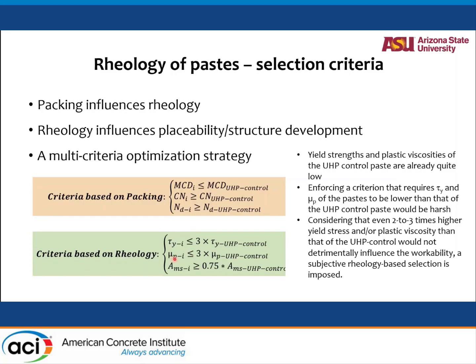For the criterion based on rheology, just saying that the yield stress of my mixture has to be less than the yield stress of the control is not very efficient, because even two to three times higher yield stress or plastic viscosity would not detrimentally influence the workability, especially when your packing is so high, right? So we took this number as 3, and we did experiments to show that you actually can have good workability in that case. So we used a factor of 3 for yield stress and plastic viscosity. For mini slump, we wanted to use a parameter of 5, but we arrived at a 0.75 multiplier of that of control. Again, these are subjective qualifications that the user can change depending on how he or she wants the properties for their mix.